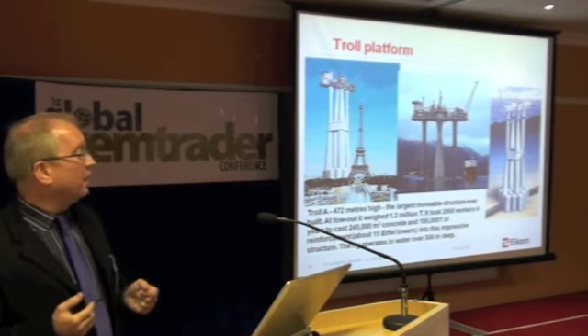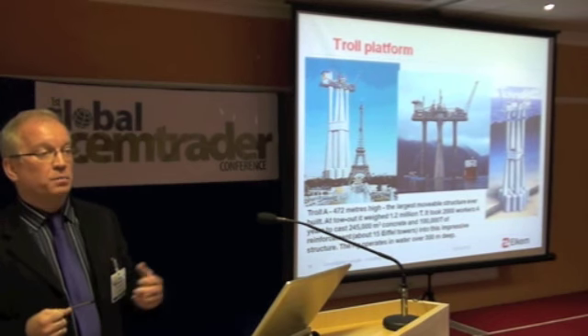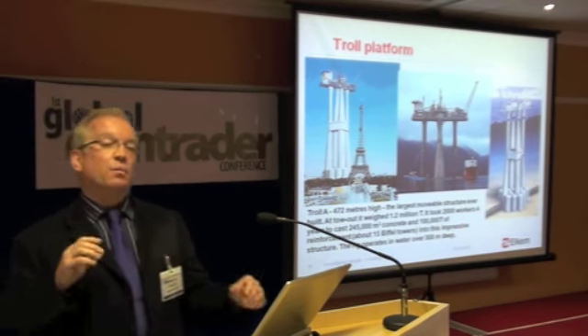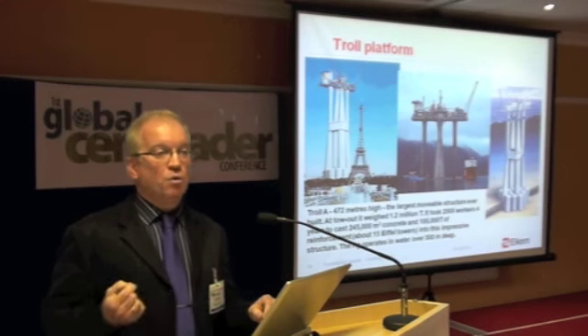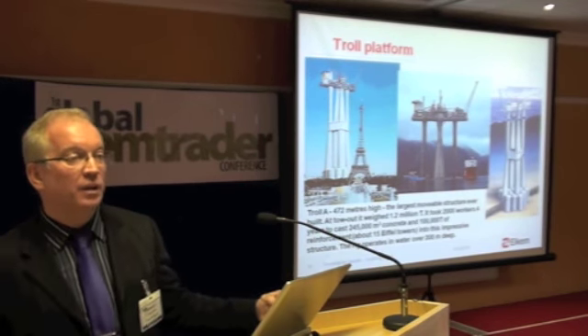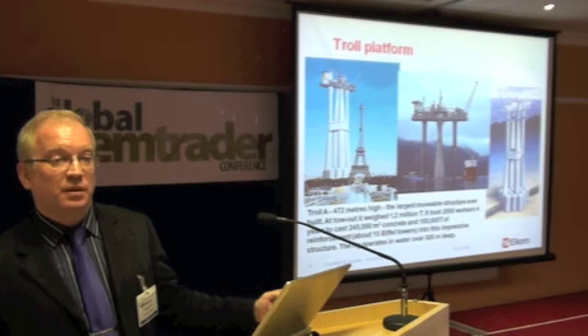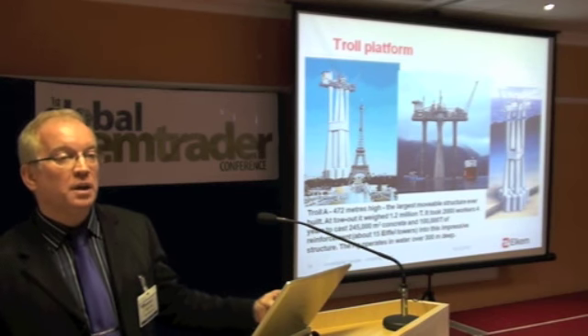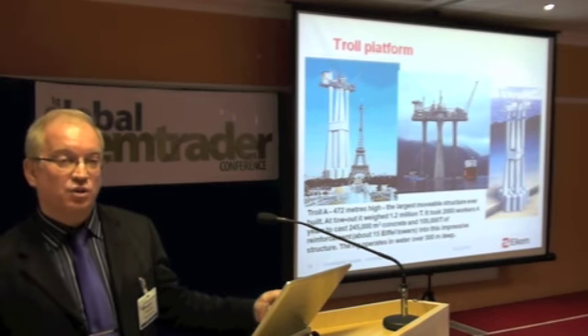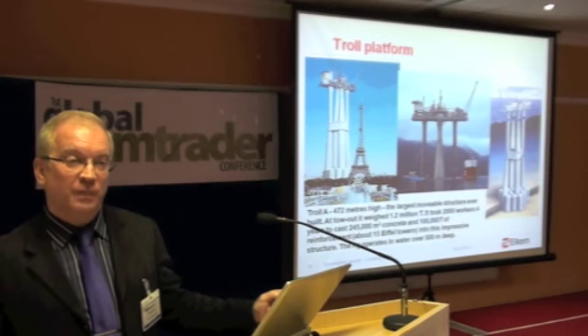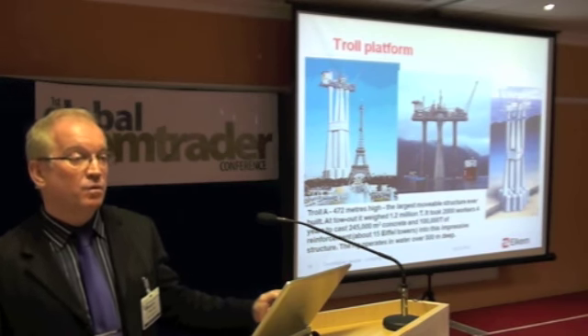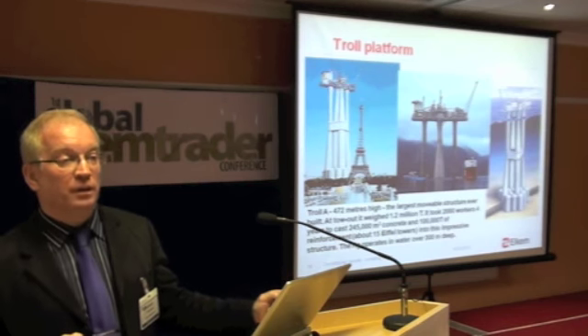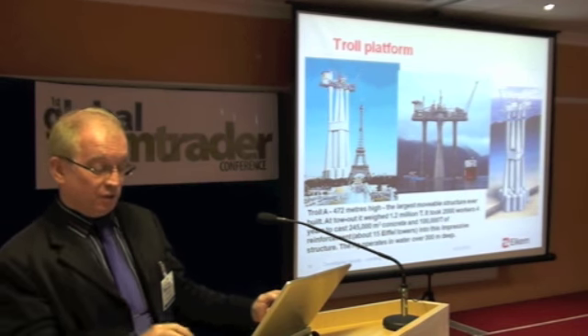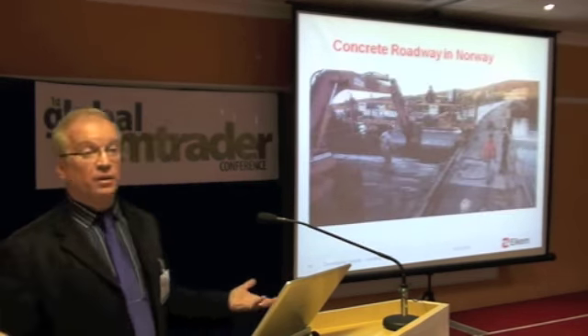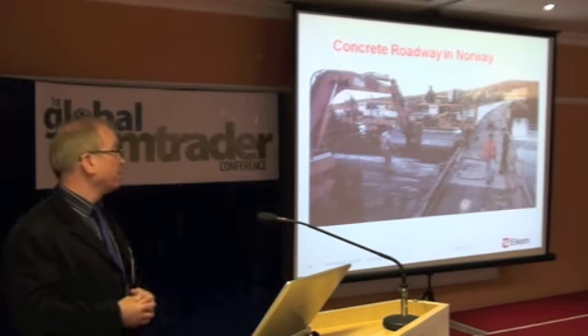And what you can see here, Troll platform, one of the biggest ones we produced, when they went back and tested the water permeability of this concrete and on others, the average is less than 3 millimeters of water penetration into that concrete. If the water can't get to the reinforcing steel, it cannot corrode it. That's the durability factor. And of course, that means they use it in the roadways.